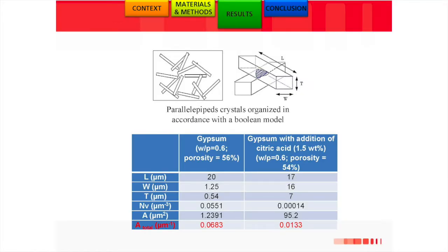So we did a small calculation to try to calculate the number of contacts in this configuration where we have needles and when we have parallelepipeds. Obviously, the number of contacts per unit length for gypsum with the additive is about 6 times lower than in